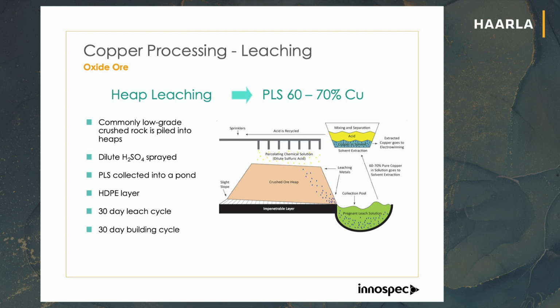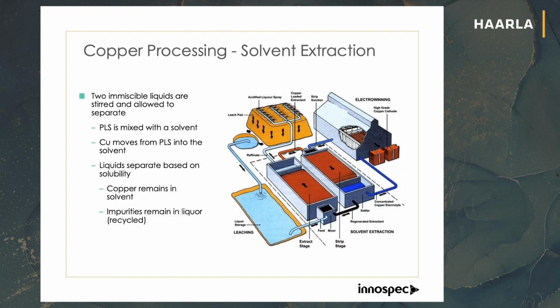One of the other processes is heap leaching, where you take low-grade material and spray sulfuric acid over it. When you're doing that, you're dissolving the copper, collecting that in a pool, and then concentrating it through the normal cycles. Once you go through that, the next stage is solvent extraction.